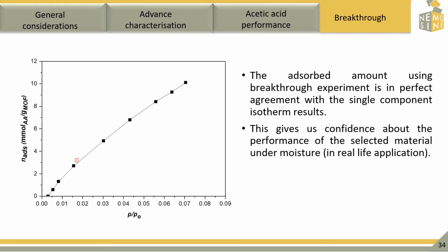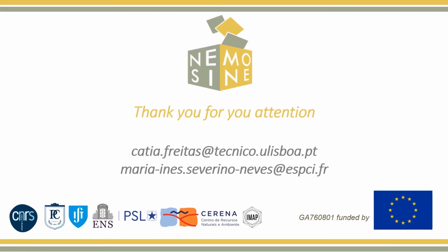If we compare the breakthrough result, the red squares, with a single component isotherm of the same material at a particular relative pressure, we can see that there is no difference between the breakthrough and the isotherm, which means that the presence of moisture did not decrease the acetic acid uptakes. It also means that the amount adsorbed dynamically is equal to the amount adsorbed in equilibrium. This is a very good indicator of the fast kinetics of adsorption under real-life application conditions, and we can also see that these acetic acid performance techniques can complement each other. Thank you so much for the attention.